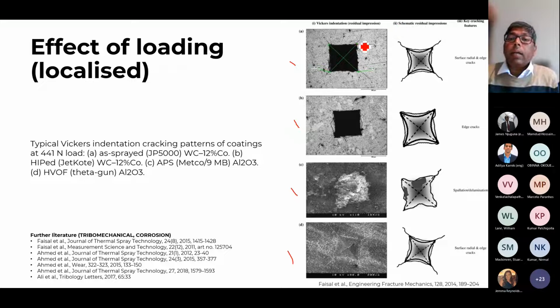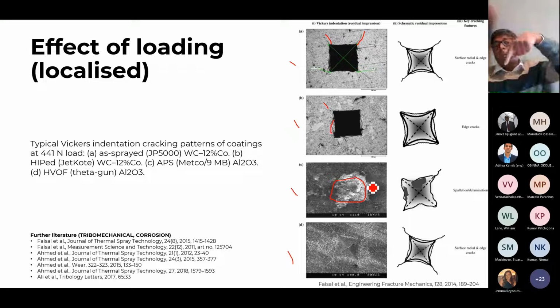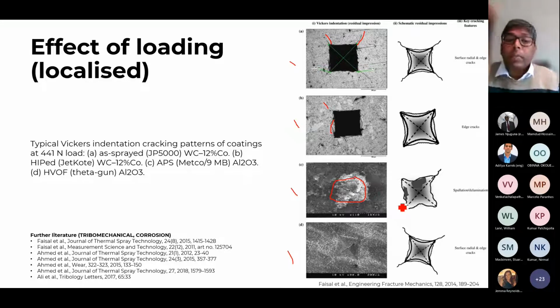It can have a crack. It can have just a chipping at the edge with no crack. It will have a very unconventional, a very different type of indentation impression on the surface. So it depends significantly on the material type. And if you've got a composite material like tungsten with cobalt and so on, again, things are different. So this is a good example where we compared the same probe, different material, different fracture will happen.